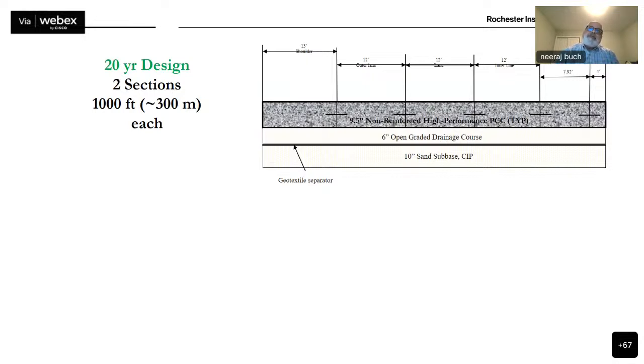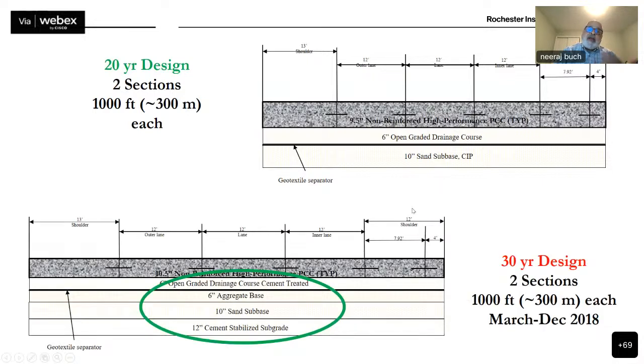And then, of course, Michigan DOT also constructed their regular cross-section pavements, which is a 20-year design for concrete pavements. So what you're seeing here on your screen is the 20-year design along Interstate 69. And again, this was a jointed plain concrete pavement with 9.5 inches of concrete slab on an open graded drainage course that was then placed on a sand subbase, which was compacted in place. And then, of course, this was placed on a roadbed or a natural subgrade. So this is what the 20-year design looked like. And if I contrast this with the 30-year design, the thickness of the slab was 10.5 inches.